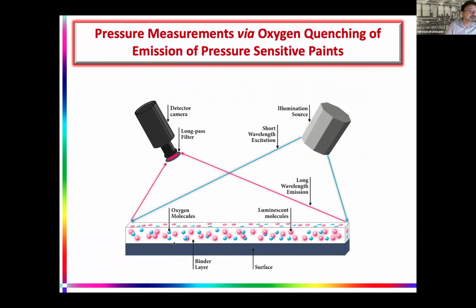Let's go now to the second example: pressure measurement via oxygen quenching of the emission of pressure-sensitive paints. Pressure-sensitive paints are actually well-known materials from the 1930s. Today they are mainly organometallic compounds such as platinum porphyrins or ruthenium complexes. They provide very strong and highly efficient emission, but if one embeds them inside an oxygen-permeable medium, some binder or even an oxygen-permeable polymer, then one can use luminescence to do surface measurements of the pressure on an object.